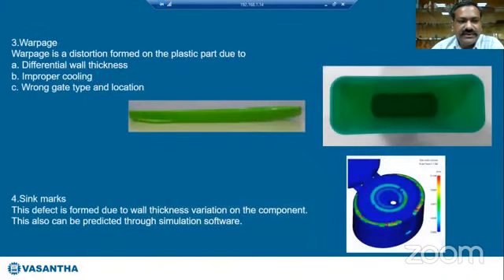And this is about warpage. This is a deformation formed on the plastic part due to different wall thickness, improper cooling on the mold, and wrong gate type and location. If a particular part is designed with an improper gate location, there is a chance that we can see a warpage effect on the product. You can see in the middle image where it is not touching the floor. Only at the center portion the component is touching and the two ends are getting opened up. This is also a defect. And on your right side, there is a tub with very thin wall section containers. You can see a warpage effect on this larger size.